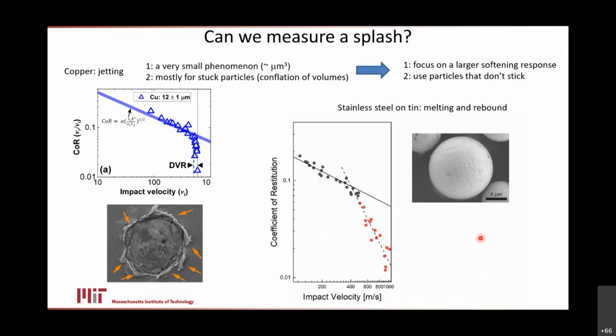And if we plot these data in the power law format, we have exactly the same thing we saw over here with copper. So there's like a plasticity regime. This is sort of the classic Wu power law. And now we have a divergence regime. But in these experiments, we've got a really big, thick divergence regime that we can go in and target and try to understand. So let me show you some of the raw data from these experiments.